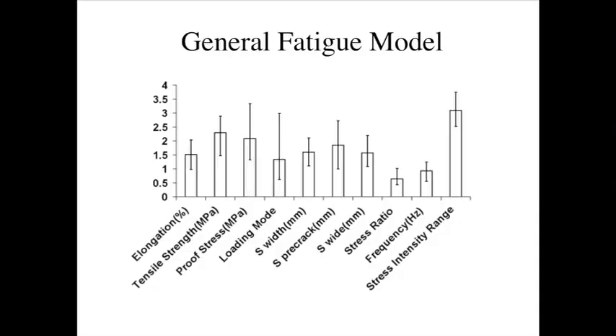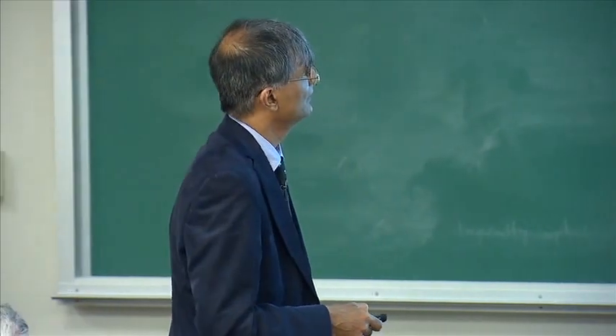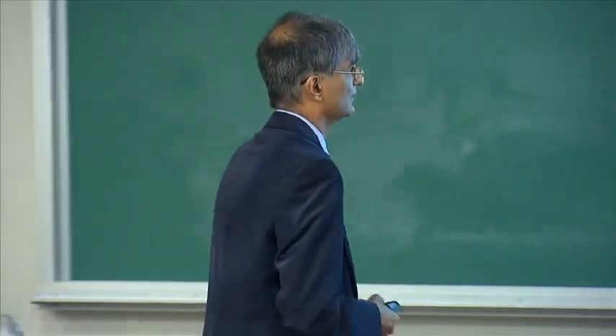Now, there are a lot of people here working on fatigue, including different variations of fatigue, like the rolling contact fatigue. But this is not about rolling contact fatigue. This is about fatigue crack propagation. And we created a neural network model which has these variables. No chemical composition, no heat treatment. So this model should apply to anything, even though it was created on data on steels. It should apply to any material. So let's see if that works.